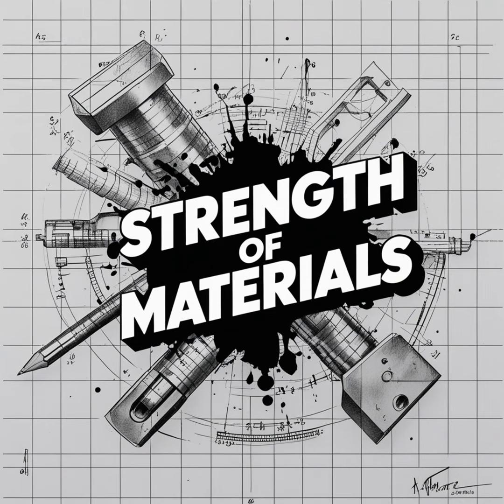It is, and the zigzag geometry induces a secondary defense mechanism known as roughness-induced crack closure. Roughness-induced closure. What does that mean physically? Because the crack path is so jagged and tortuous, the two faces of the crack aren't perfectly smooth mirror images anymore. During the unloading part of the fatigue cycle, as the metal tries to relax, those jagged, mountainous edges actually rub against each other. They wedge together behind the crack tip, effectively propping the crack open. Wow, so the jagged edges act like a doorstop. Yes, they physically shield the tip of the crack from experiencing the full range of stress during the next cycle.